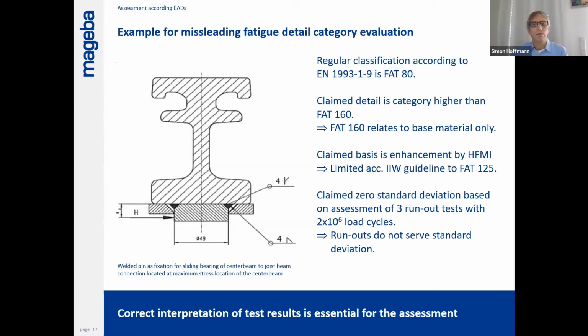And it was claimed on the basis of enhancement by HFMI, which is clearly defined with a limit according to the IIW guideline to a fatigue category 125. Furthermore, this was all done based on 3 run-out tests on 2 million load cycles, while run-out tests do not serve for standard deviation. They do not allow for proper evaluation according to existing codes and guidelines. So really be very careful in this regard, because we saw much misleading analysis.